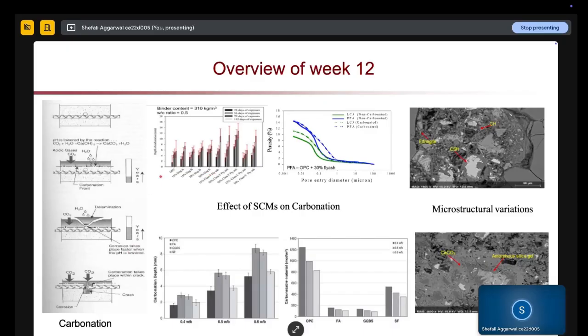So how will SCM affect your carbonation? In case of SCMs, when you are using, let's say, fly ash or LC3, your initial calcium hydroxide will be less. So initially itself your depth of carbonation will be much more as compared to your OPC system. So if you can see here, it is 28 days of exposure, 56, 70, 112 different days of exposure. In case of your SCM, your depth of carbonation will be much higher than in your OPC system, because your presence of hydroxide is less. So CO2 will penetrate much faster as compared to your OPC system.